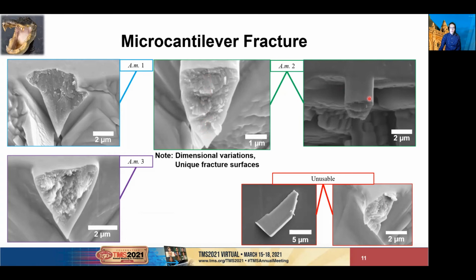This top-down image shows that the fracture surface is not completely perpendicular to the cantilever, but actually has a little bit of slant to it. In each case, the microstructure is clearly influencing the cracking behavior. These beams on the bottom here had fracture surfaces that made the calculations impossible for stress and strain, but the highly oblique surfaces add more evidence to tell us that the alligator enamel is capable of guiding cracks. This is a critical characteristic for improving the damage tolerance of enamel.